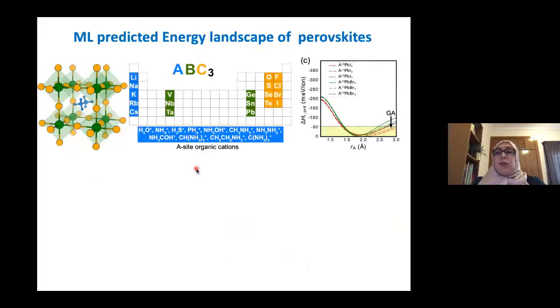And then what I want to show you is that we came up with a machine learning model. You can see the results of the machine learning model. This is the 2D demonstration of this machine learning model. And it helps us to estimate the stability of a given composition. So in this case, these are lead iodide and these are lead bromides. So it helps us to define the stability of certain compositions as a function of the radius of the cation. Each of those cations that you see here is moving from smaller to larger cations. And you can see that with this model, we can identify the stability regions for a given composition, and we can even find the optimal cation radius that could better stabilize these materials.